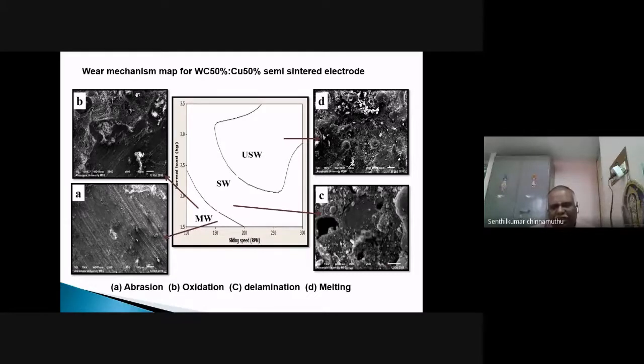That is, if the sliding speed is increased and the normal load also goes beyond 2.4, the coated particles get delaminated from the surface, so that severe wear occurs. This zone is called the severe wear zone.